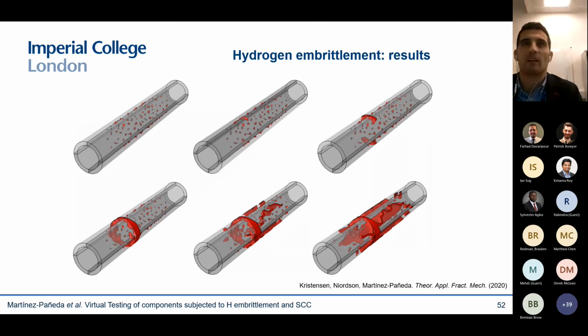And I should emphasize that this looks a little bit like a video game, but it's actually quite a sophisticated calculation that involves multiphysics modeling and that is resolving pits that are on the order of hundreds of microns or smaller over a 3-meter component. And we can do that in a fully parallelized manner such that it runs in a few hours. So we have a tool that allows us to predict when cracking will initiate, how fast it will propagate, and when do we need to replace our component.